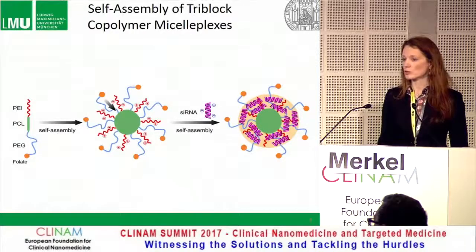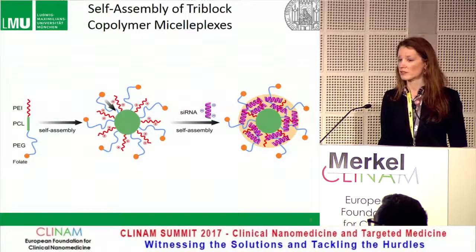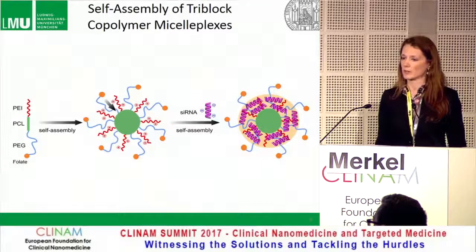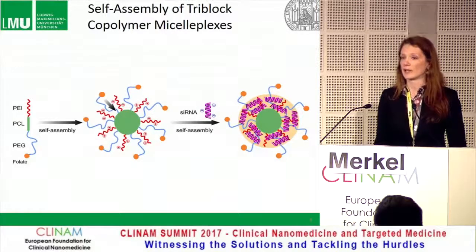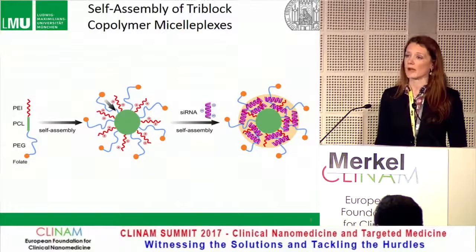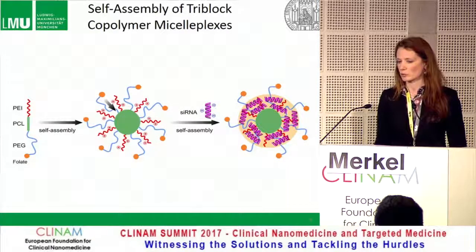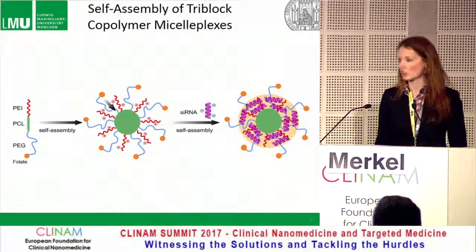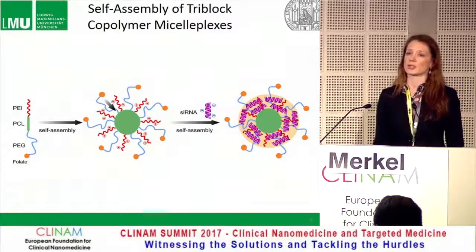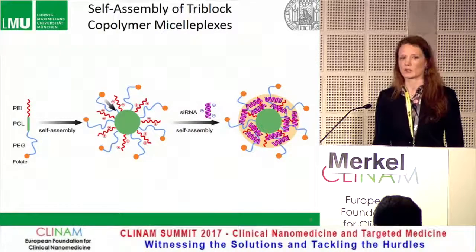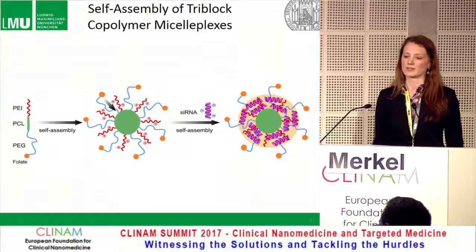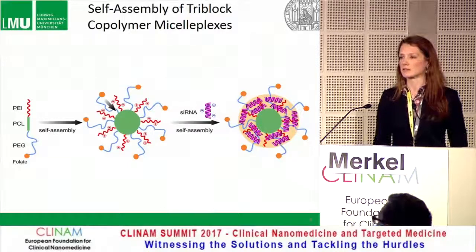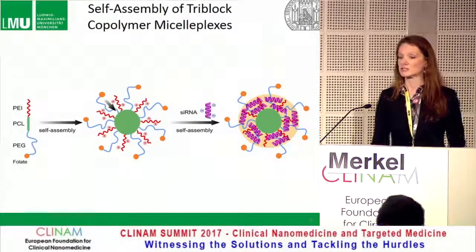The materials we use are tri-block copolymers made of three different blocks: a polyethylene imine block, a polycaprolactone block which is the hydrophobic part, and a polyethylene glycol block. We can also attach targeting ligands, which I won't talk about today. The system is quite versatile and we can change it to whatever needs we're trying to address.